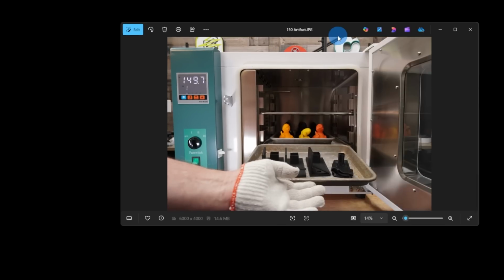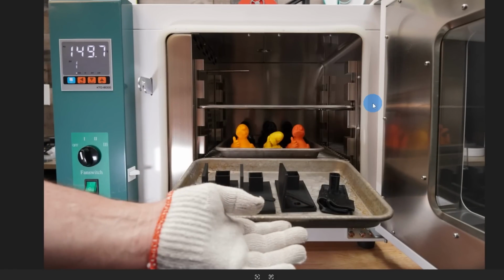And finally, the artifacts at 150 degrees. This is PC Max, and it did some strange stuff. We're going to look at it up close here in a minute. Silk PLA, really, it started to sag over on the wall. You can see that. But other than that, not anything real bad.